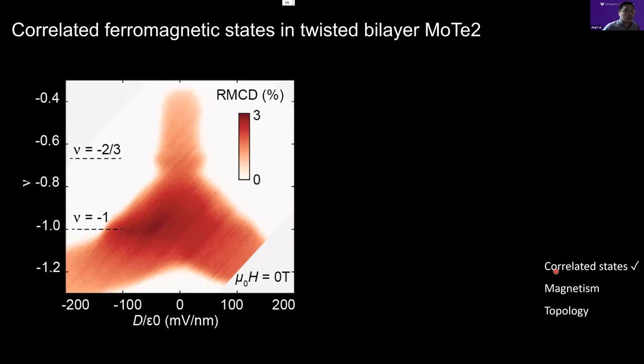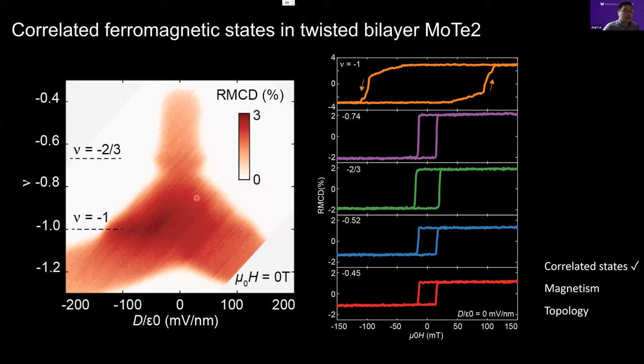Okay, so having checked the correlated state, the next step is to check magnetism. We can perform magnetic circular dichroism on our sample while changing the carrier density as well as the electric field applied, which is an interlayer bias between the bilayer system. What we can see is that at zero electric field, as a function of doping level, we can see the enhancement of the RMCD signal at the fractional fillings as well as at nu equals minus one. And if you take a line cut and look at the magnetic field dependence, you can clearly see the hysteresis loop at the integer filling as well as the continuous magnetic states below nu equals minus one.